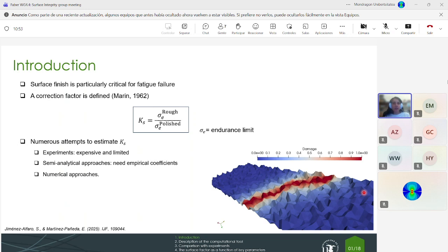This is very clear in materials such as steel, for example, where the endurance limit is really clear. It is the stress level at which we have infinite life. But for materials where we don't have it, normally they put a reference point at about 1 million cycles. So for this surface factor, we can find numerous attempts to estimate it in the literature. We find experiments, but in my opinion, they can be really expensive and sometimes limited.